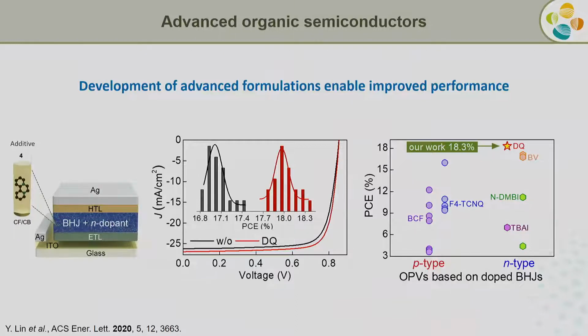In addition to the interlayers, we also work on the photoactive layer. And what we do there is trying to improve the efficiency with which it converts photons to electrons. And one way we have identified that was quite interesting is to add small molecules as a third or fourth component in that blend of semiconductors, which is rather complicated in the case of organics. But what we found is that by adding this small, what I call salt and pepper in our devices, we can improve, tune the performance of these devices.